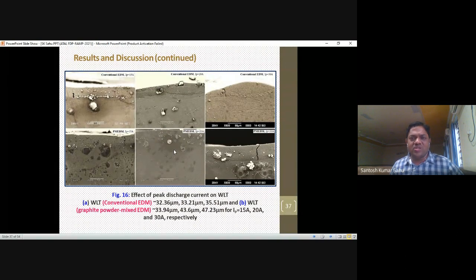Current varies from 15, then 20, then 30. Then again, with powder mix EDM, we have the same variation of current: 15, 20, and 30. Then you can see the white layer thickness increases after adding the graphite powder. So here we can see the thickness. The increased energy input causes more material to be removed from your workpiece, but the dielectric fluid appears increasingly inefficient to sweep away the debris from the machining zone.